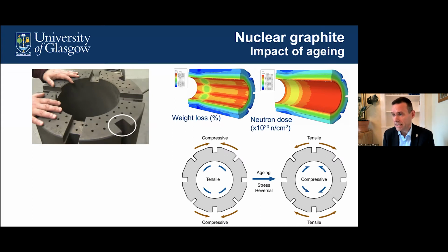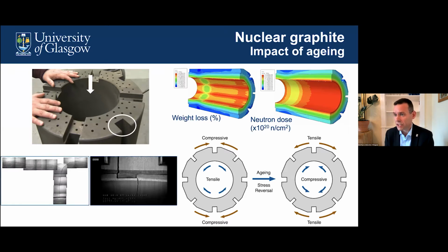What you'll notice is that we have these keyways around the outside of the individual bricks, which are there to allow interconnection of the bricks in the reactor. But they also act as fantastic stress raisers in a situation where the brick is experiencing tensile stresses on the outside. If you look at routine inspections down through the fuel channels into the inside of these graphite bricks, you can see crack patterns that have been observed. On the left are so-called bore cracks, and on the right are so-called keyway root cracks. These have been observed over the last few years in some of the older power stations.